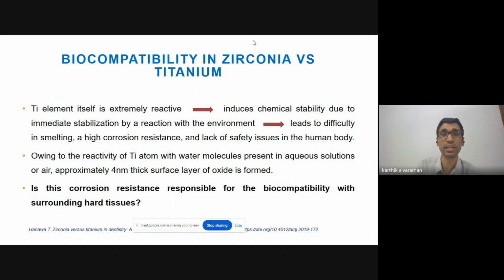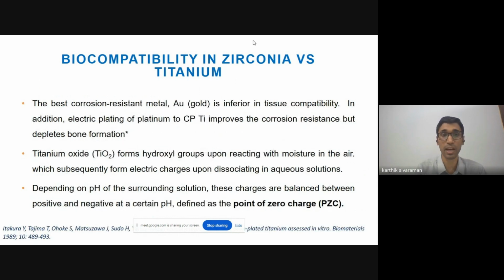What I mean here is, if a material exhibits very good corrosion resistance, does it mean that it's very biocompatible with the surrounding tissues? The answer is no, because there is gold, which is an extremely corrosion resistant metal, but it's found to be inferior in tissue compatibility. Studies have also shown that when platinum was electrically plated onto titanium to increase its corrosion resistance, it did improve the corrosion resistance, but it reduced the bone formation.